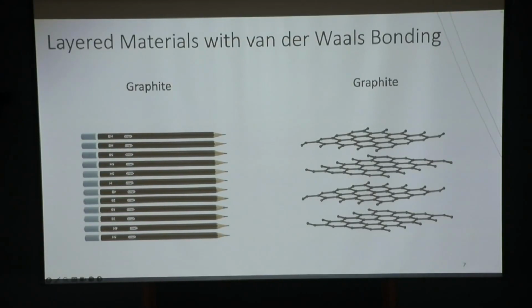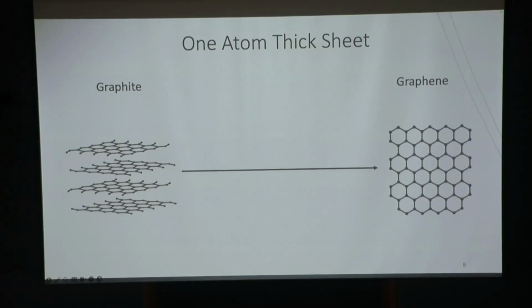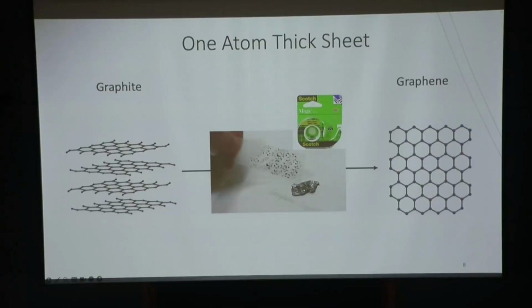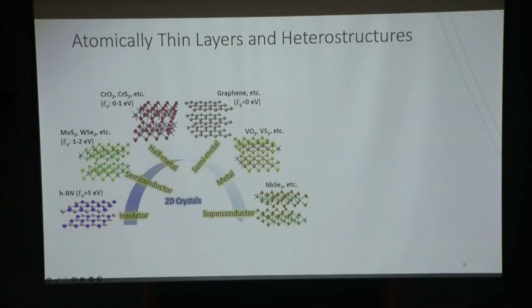So the question is, can we control this exfoliation accurately enough that we can get a single atomic layer of this graphite? That turns out to be doable. All you need is a Scotch tape and a lot of patience. So you use a Scotch tape to continuously exfoliate this graphite. And after some time, it's actually possible to get down to a single layer of graphene. Very soon after the observation of graphene, people realized there's really a host of material families that you can play with. They are layered van der Waals heterostructures, and you can use Scotch tape to exfoliate them down to a monolayer or few-layer limit.